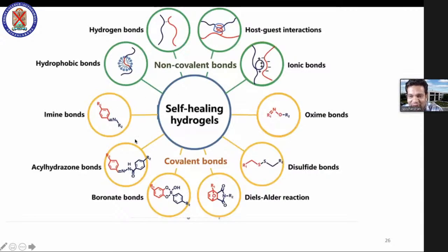Covalent bonds work by mutual sharing of electrons. We have imine bond formation, acylhydrazone bonds, boronate bonds, the Diels-Alder reaction, which is the first self-healing material, disulfide bonds, and oxime bonds. The non-covalent bonds are hydrophobic interaction, hydrogen bonding interaction, host-guest chemistry, and ionic bonds. The non-covalents are physical interactions. Of course, they work as a self-healing material, but their lifetime compared to covalent bonds is low. After a certain time, they start breaking the bond with the host-guest material, or the ionic or hydrophobic interaction.